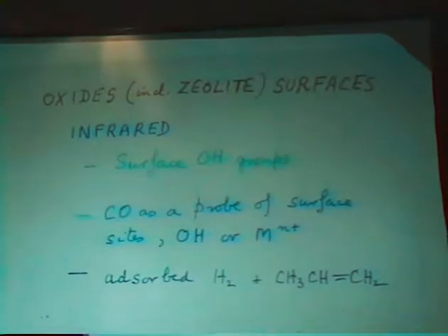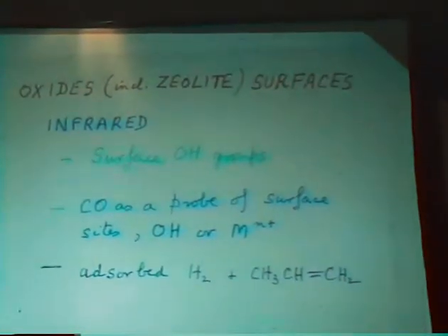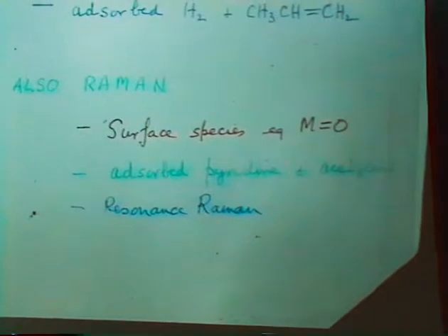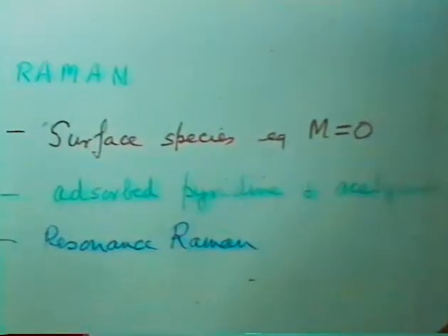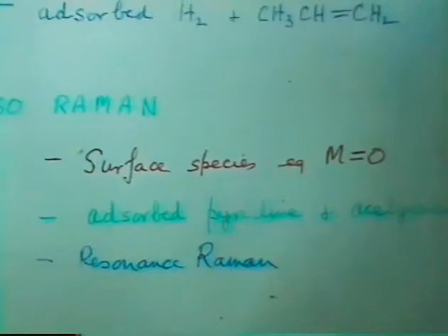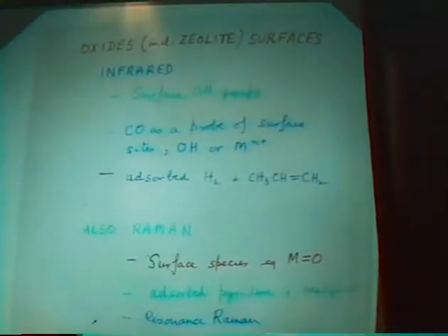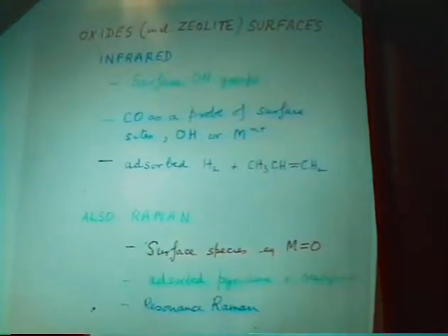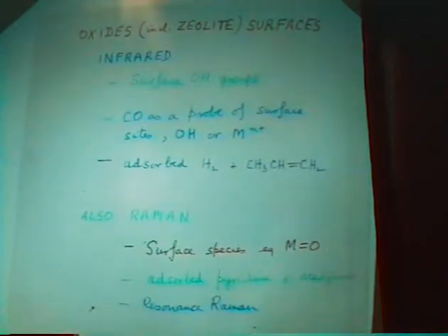Right, okay, fine. Well, now let's look at the oxides, and here I can move more rapidly because, not surprisingly, I chose some of the same examples that Keith Hall chose yesterday to show work on the oxides. But here I want to bring out the Raman contribution. By infrared, you can look at the surface OH groups. You can use CO as a probe of the different surface sites, like different metal sites. You can look at adsorbed hydrocarbons. But also, you can use Raman spectroscopy, not only to study the surface of the oxide itself, but also the acidity of the adsorbed species.